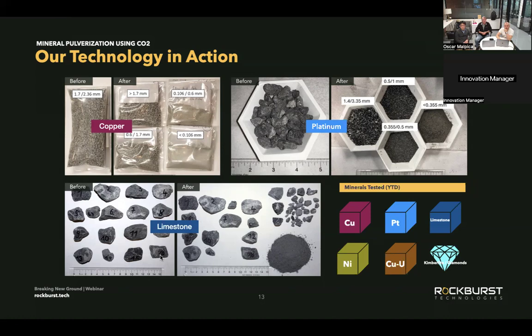And then in the bottom left, we've got limestone, a softer material. This is a very early picture from a number of years ago when we were just, I think, proving out our first test rigs. And these examples are just showing one cycle of our process where you put the feed in and you do that one breakage, a rapid depressurization breakage cycle, and you produce a certain amount of fracture across the size ranges, but some of that fracture is going to be at the product size that you want, say sub 100 micron. And then the oversize, of course, goes back in for another cycle.